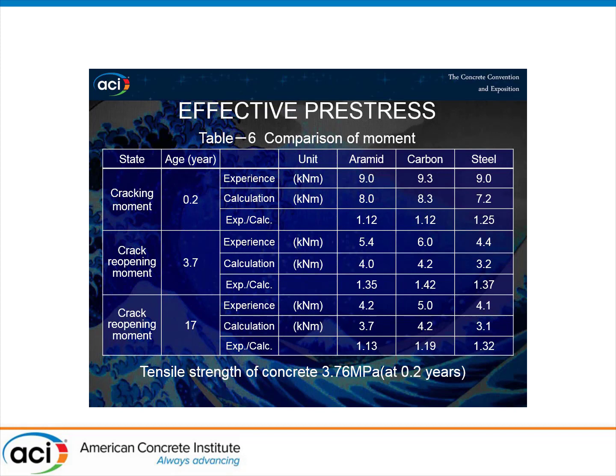This table shows the comparison of the cracking and crack reopening moment. The experimental is the measured value by loading tests using crack gauges attached to the cracks. And calculation is the value by a previous back calculation. The measured values were larger than the calculated value, and it became clear that the relaxation rate chosen for the material test was a relatively appropriate value for the specimen with long-term exposure.